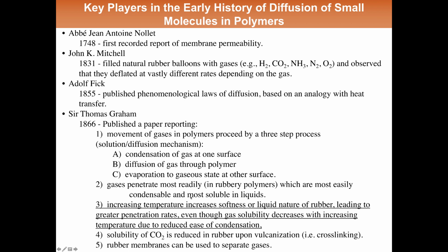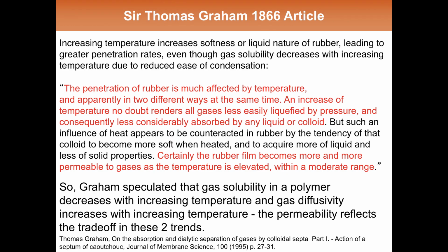He found through his studies that increasing temperature led to greater permeabilities, even though the gas solubility decreased with increasing temperature. So this comes back to a notion of the solution diffusion model. That is, as the temperature goes up, all the gases are less soluble, but the film becomes more and more permeable to gases as temperature goes up.